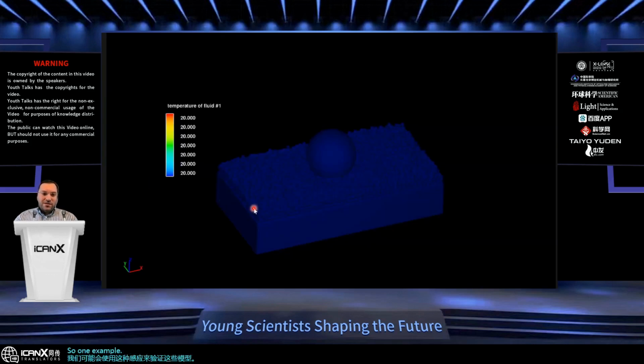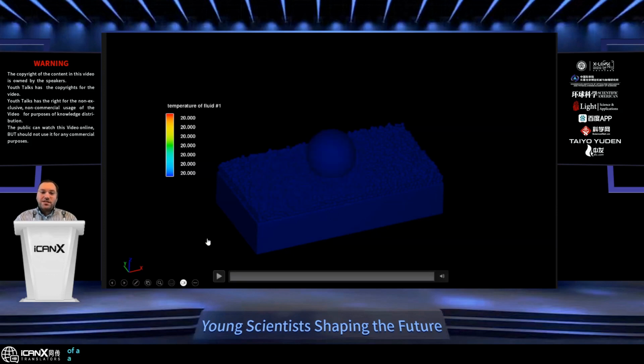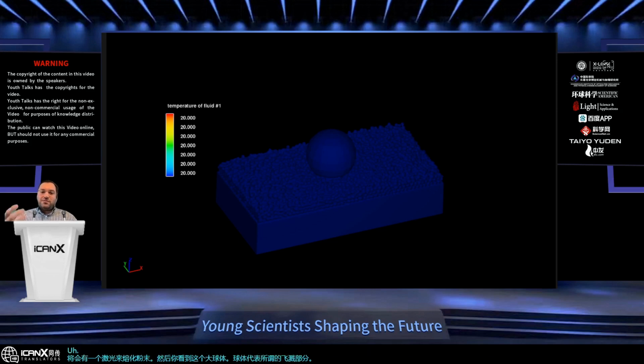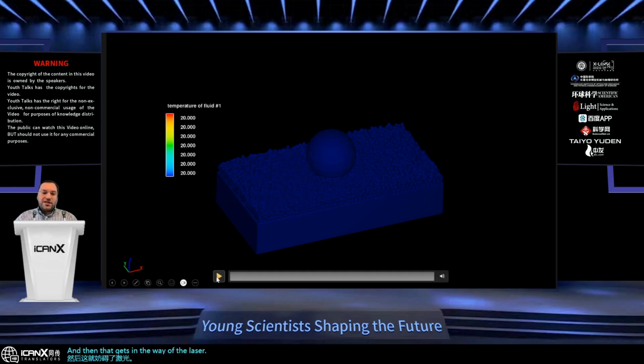So one example of a computational model, and this will give you some idea of what the melt pool looks like. So this is the simulation in powder bed fusion. There's powder on top of a substrate, and there's going to be a laser that comes and melts the powder. And then you see this big sphere. The sphere represents what's called a spatter particle. And during these processes, you can have powder and liquid that gets ejected out of a melt pool that falls somewhere else. And then that gets in the way of the laser at various locations.